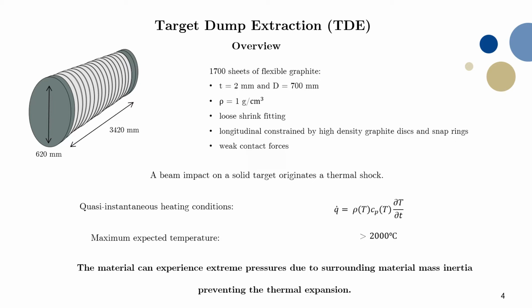The sheets hold together with weak contact forces. What happens when a beam impacts a solid target is that it can originate a thermal shock due to the collision between the particles, that is, the protons and the nuclei of the solid material. This collision occurs in a very short time called the deposition time, and a large amount of energy is delivered from the particles to the material, and it is transformed into heating very suddenly, in quasi-instantaneous heating conditions. With these values of density one can expect a temperature that can exceed 2000 degrees Celsius. Due to this thermal shock, the material can also experience very high pressure due to the surrounding material's mass inertia that prevents the thermal expansion.